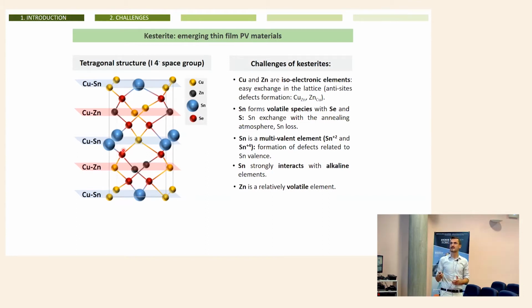Why? Because first, you can note here that copper and zinc are in the same plane or share the same structural plane. And copper and zinc are structurally identical, are isoelectronic elements. So an exchange of copper and zinc in this plane is very easy from the thermodynamic point of view. And this introduces disorder in the material and can introduce defects that kill the photovoltaic properties of your material.